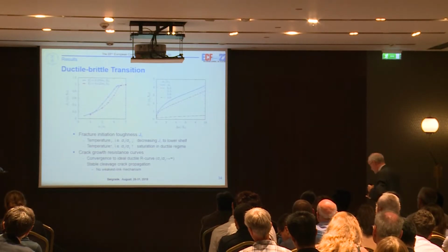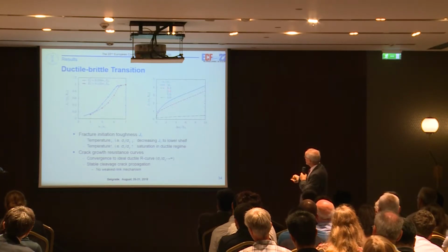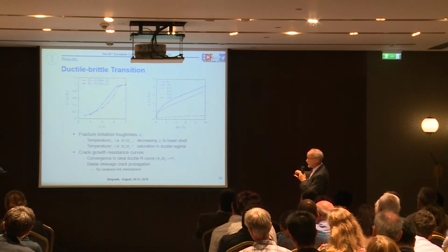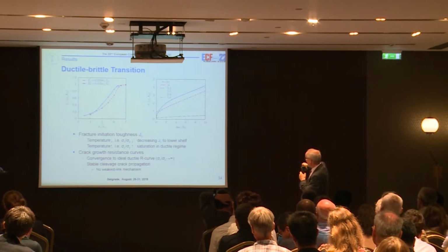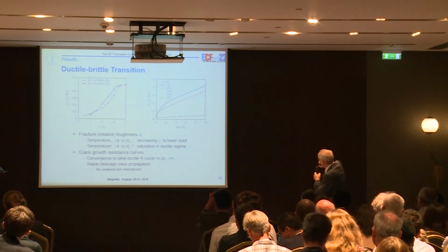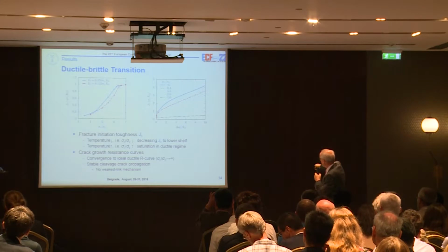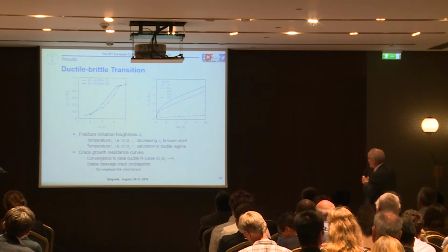So these are R curves. They are shown here for these ratios. The blue one is the ductile one, where the ratio is infinite. And if we decrease the ratio, we come to more and more brittle behavior, and this is a very typical sign of the ferritic matrix.